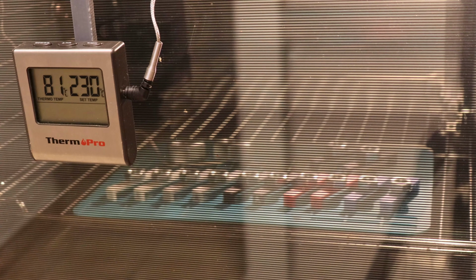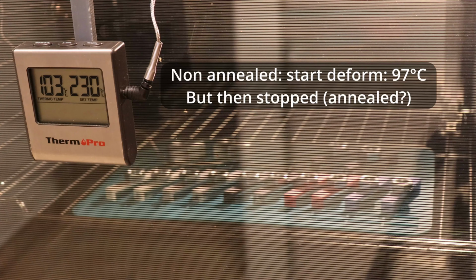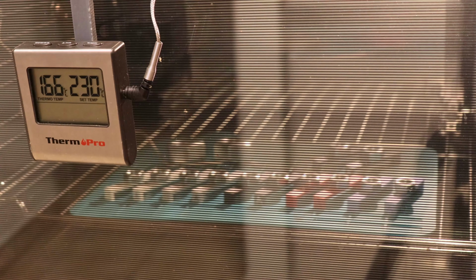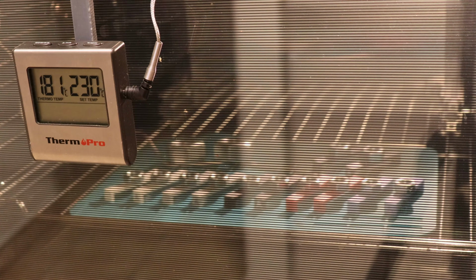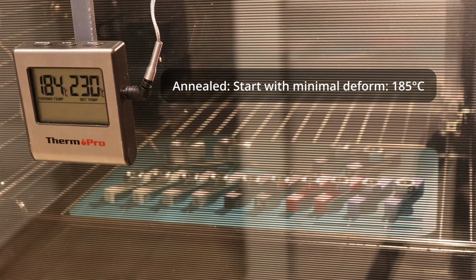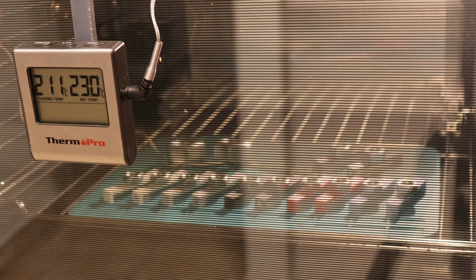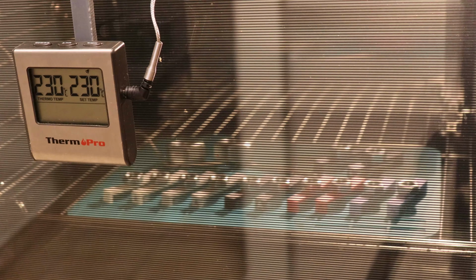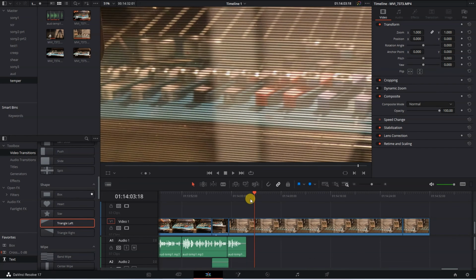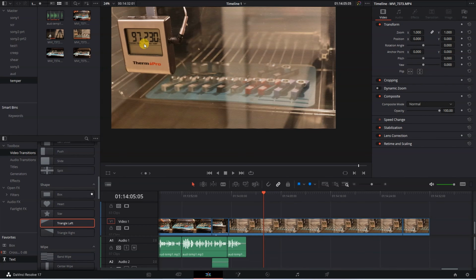The first minimal deformation on non-annealed test objects I noticed at 97 degrees Celsius, but they stopped deforming. This I noticed with all semicrystalline polymers. They became annealed during my slow testing process. For annealed objects, much later, at 185 degrees Celsius. And none of the objects deformed completely, not even at 230 degrees Celsius when I stopped the experiment. All this I could notice only by analyzing the footage frame by frame, and this is just one example of my method.